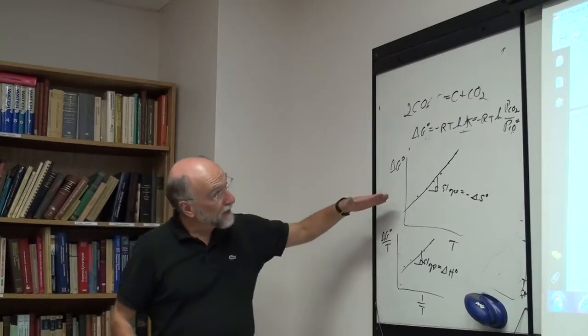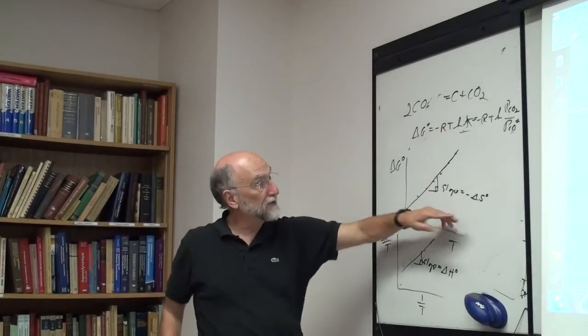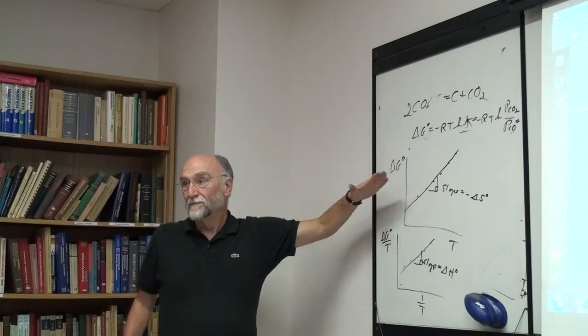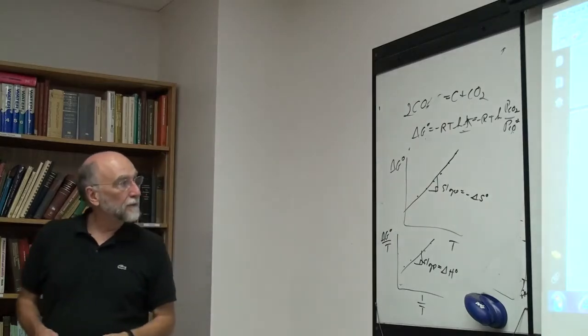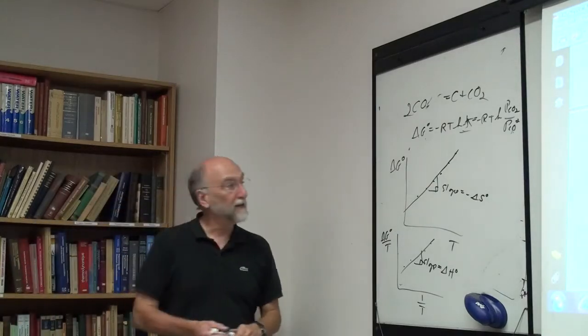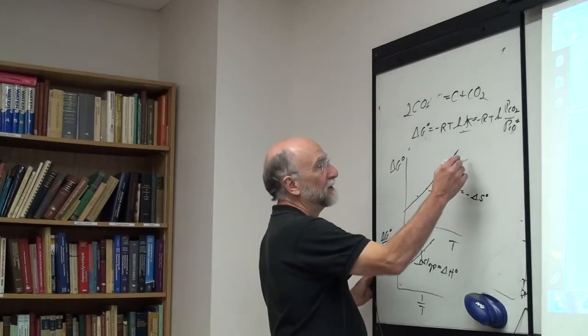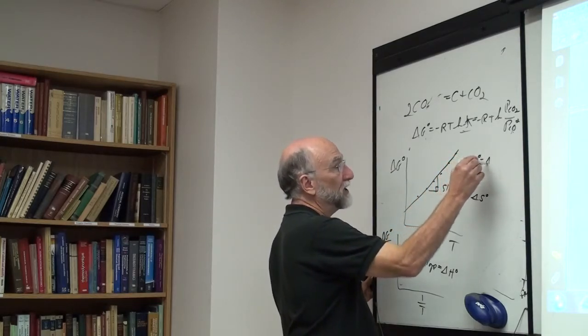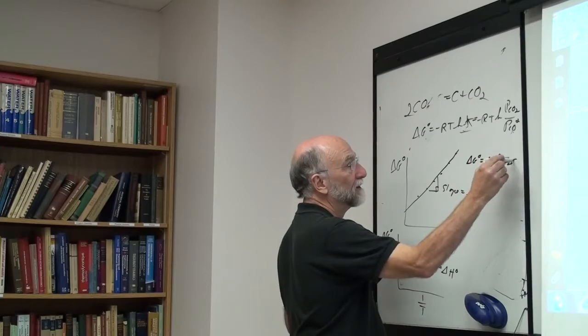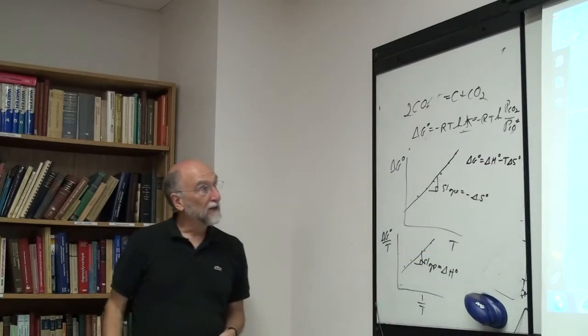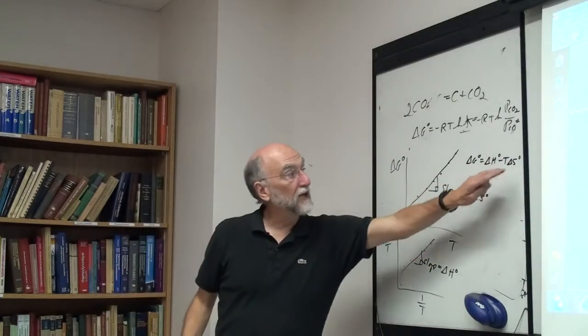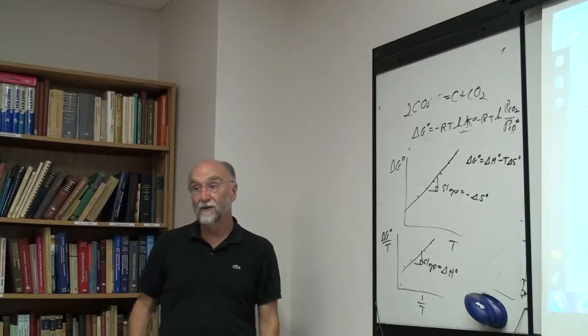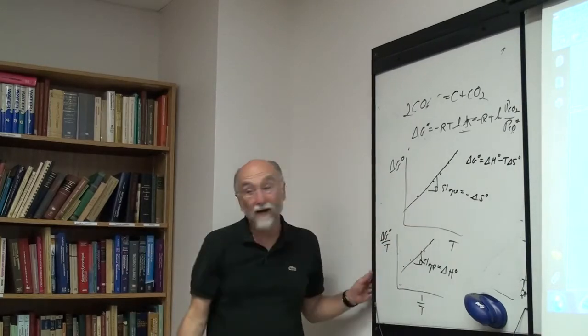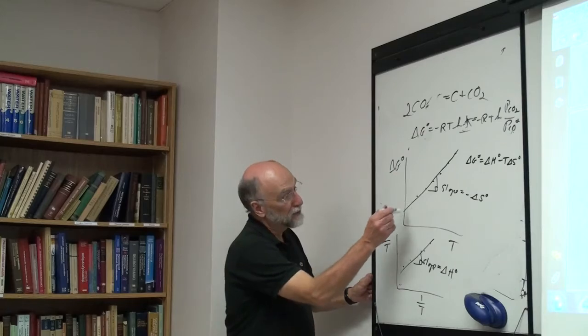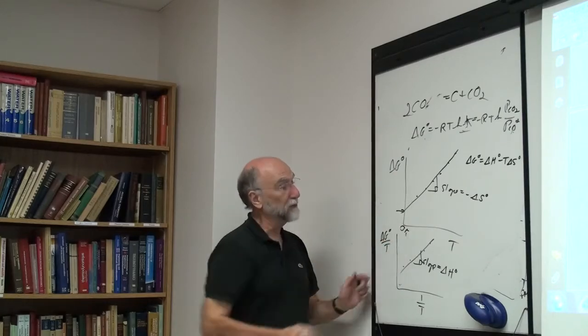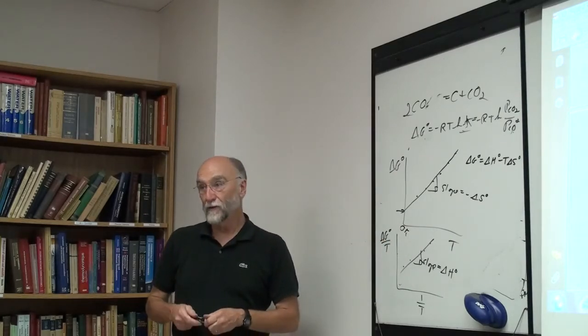This doesn't have to be a straight line, of course. This can be a curved line. In that case, delta S will vary with temperature. Suppose it is a straight line. Okay, then we know that delta G is delta H minus T delta S. Now, if it's a straight line, that means delta H and delta S are constant, independent of temperature. In which case, obviously, the slope is minus delta S. And if I were to extrapolate this back down to 0 Kelvin, that would be the heat of the reaction.